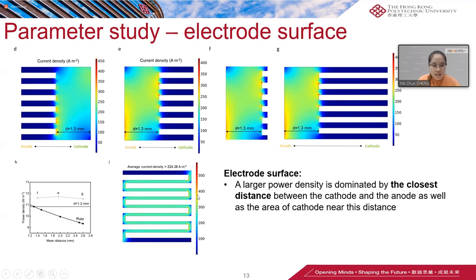The power density in figure E to G are predictably higher than those of the plate electrode with a distance of 1.3 millimeter. However, the power density stabilized at approximately 11.5 watt per meter square rather than increased with the cathode area. When exclusively taking the cathode area into consideration, the results seem inconsistent with our hypothesis. This can be explained by the current density distribution in figure E